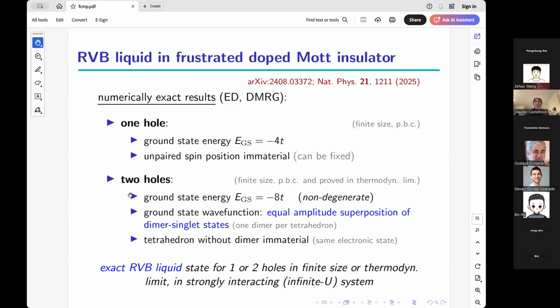In fact, you can even put two holes in the system, and you realize that the ground state energy is exactly minus 8t. The ground state is unique. In this case, here you have the unpaired spin position that gives you some trivial degeneracy. This is unique. The ground state wave function is again the equivalent superposition of all nearest neighbor singlet states. And now there is a subtlety about the tetrahedron without dimers being immaterial when you write it in electronic states. Maybe this is a higher level comment that I can explain for those who are interested in understanding more of the details.